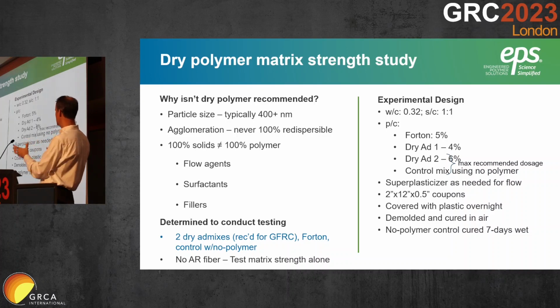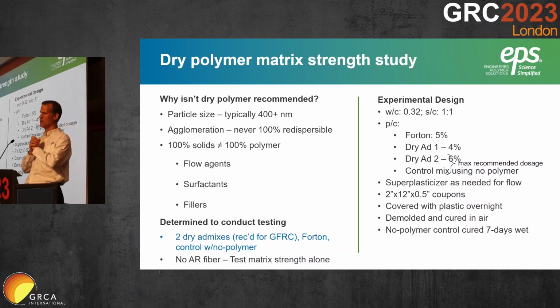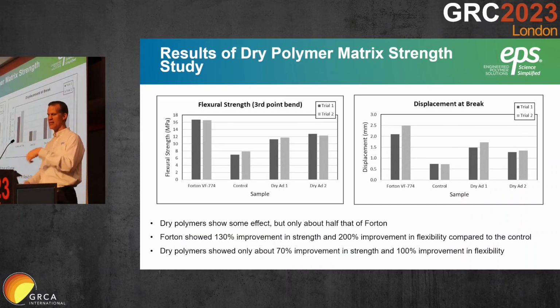Cast coupons 2 inches by 12 inches by ½ inch, covered with plastic overnight, demolded in the morning, and cured in air the rest of the time, except the no polymer control was cured with the 7-day wet cure. At the end of the 7 days, we tested the flexural strength using the third-point bend test. You can see the results there. We've got the flexural strength on the left, generally correlating to the LOP of the materials. On the right you've got the displacement, or the flexural strain at break. You can see the control down there, the dry polymers on the right, Forton on the left.